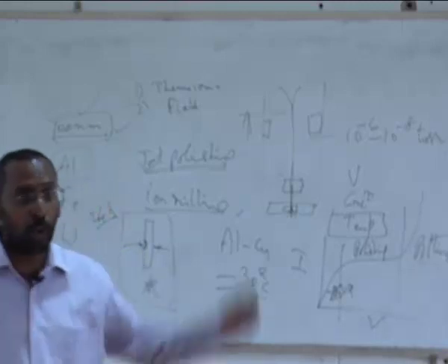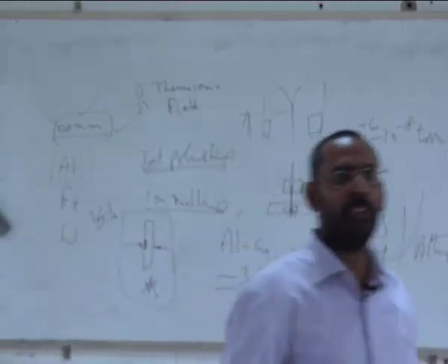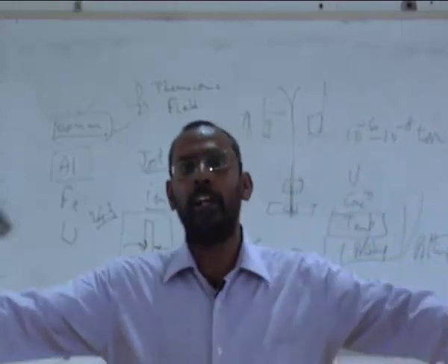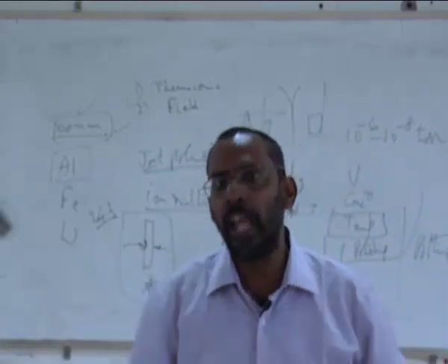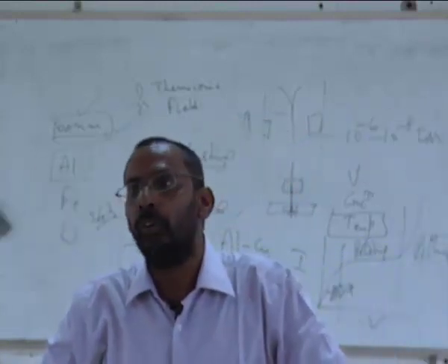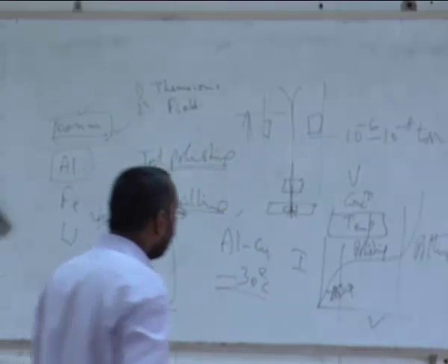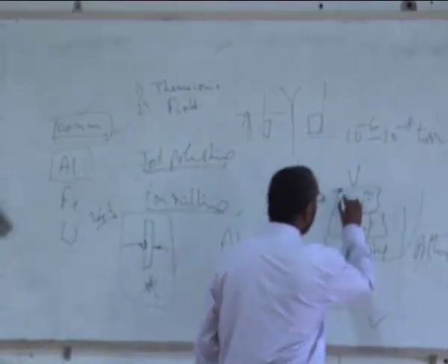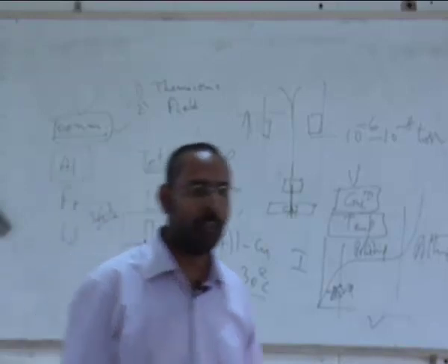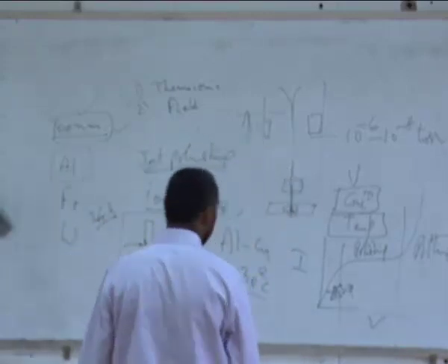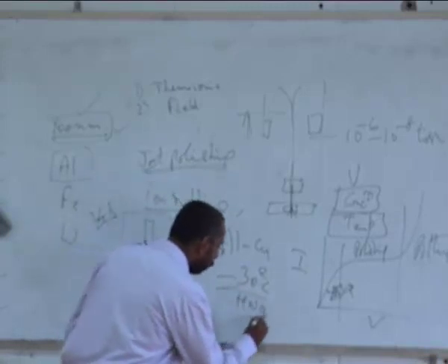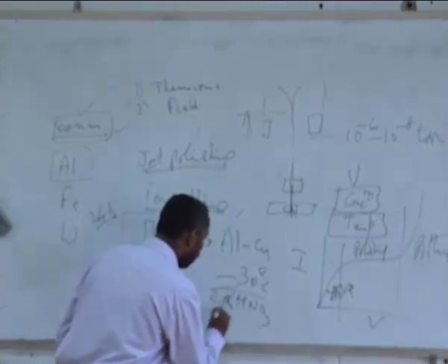So you cool the whole electrolyte to very low temperatures using liquid nitrogen or something, and then keep the electrolyte at low temperature and allow it to circulate and then fall as a twin jet onto the sample and do the whole thing. And also what is important is what concentration you are using for different solutions. For example, for aluminum alloys, the best solution that is used is 20% HNO3 in methanol.